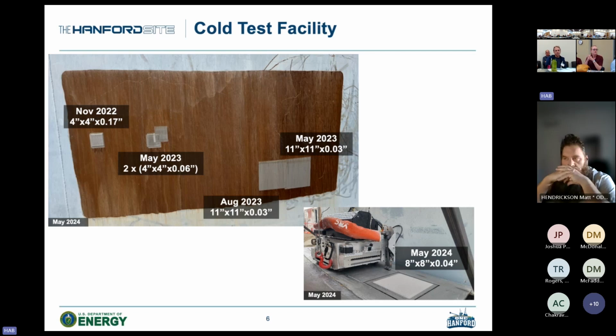I'm showing you these. It basically shows you the validation that we can deposit a thick patch if desired. We're shooting for something greater than 1/8 of an inch thick, and we actually came up more like 1/6 of an inch that we placed down. We also showed how you can overlap patches with each other. So there's no problem if you needed to butt them up against each other to either go over it again to add additional thickness, or if it needs to be extended, you can spray over top an existing patch.